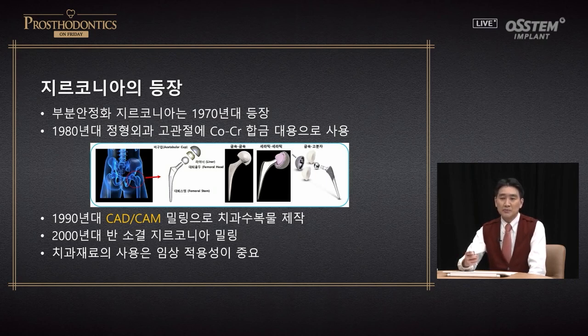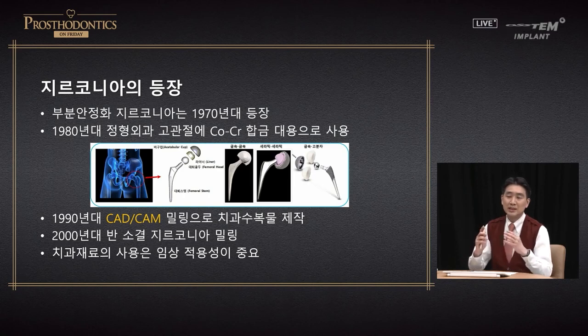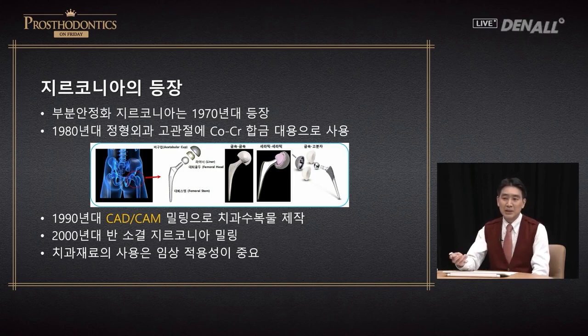As you know, the first zirconia system was fully sintered. It was very hard and there were many problems. There would be wear on the burr. 10 years passed, and in the 2000s, half-sintered, so not fully sintered, zirconia was introduced. And you would cut that zirconia. And with that, the era of zirconia started.